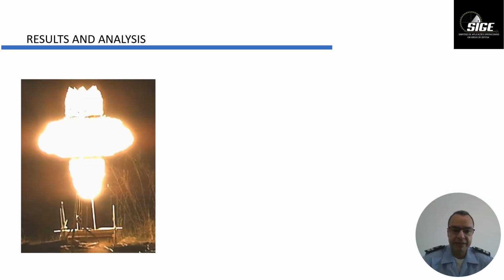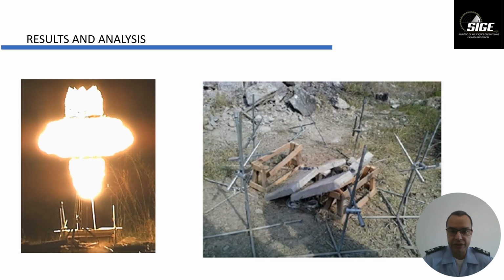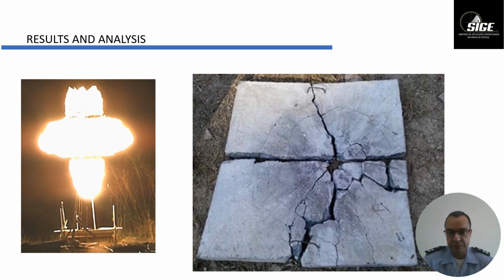So for the results and analysis after the explosion, here we can see one of the explosions of one test that we are going to analyze. We are going to analyze two tests, from two different papers, two different works. Here is the first one, and after the explosion we can see that the slab was completely destroyed. It's level 4. Here we could put the parts back in their original position, and we can see the part where the shock wave hit the slab and caused that damage.